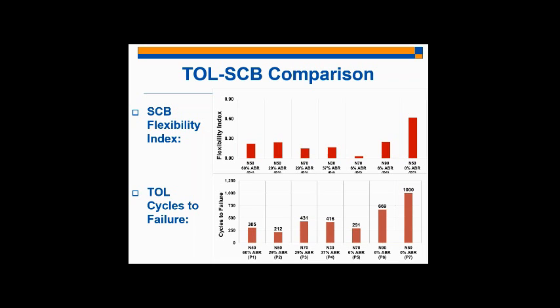And for our best performing mixture, there's a match or correlation between their best performing mixture, P7. So the two extremes of these two tests are matched. Good mixtures match and poor performing mixtures match. There wasn't such a great match in the middle region between the good and poor performing mixtures. But we can say that the very different mixtures are identified in both the SCB and the TOL cycles to failure.